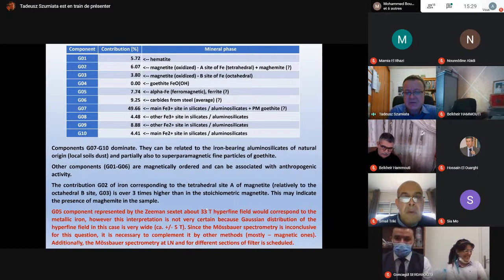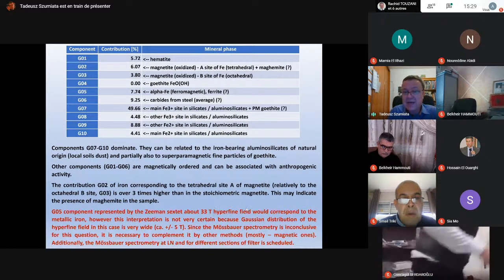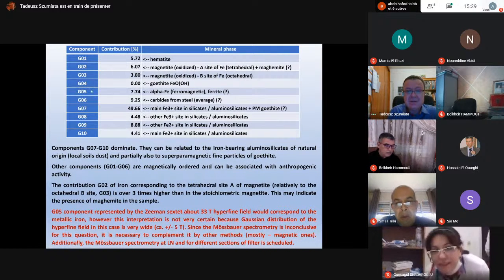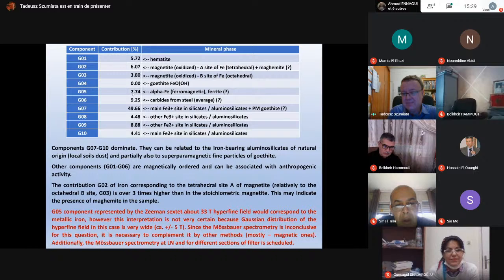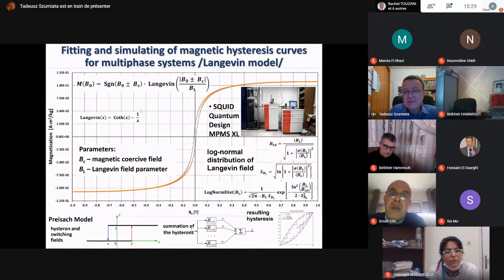There is some component of 33 Tesla, which is a value of typical characteristic hyperfine field for metallic iron, and there is something. It is this component of about 7% abundance, but it is very wide. So we cannot say definitely. Mössbauer spectrometry is inconclusive in this question, but it gives some arguments for the presence of metallic iron, but it demanded some further investigation. We decided to make just magnetic measurements, magnetic hysteresis curves, using SQUID Quantum Design. It was made by our colleagues at Warsaw University.